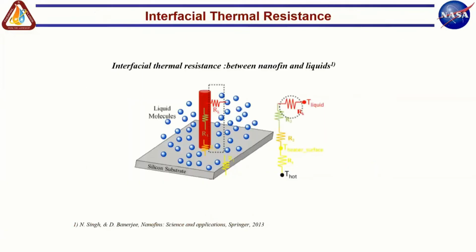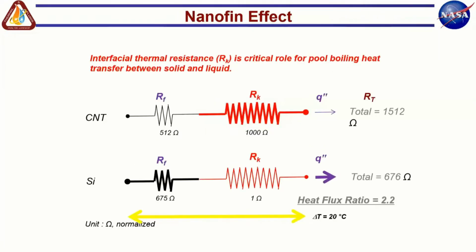So, if you think of this whole nanofin as a resistance network, if you do the numbers, the ones that dominate are the fin resistance and the Kapitza resistance, which is marked as RK. And if you do the numbers, the back of the envelope estimates using a one-dimensional conduction model. If you look at a carbon nanotube, and I have normalized the numbers here, these are non-dimensional numbers, even though I'm calling it ohms, it's not really ohms, just for your visualization purposes. So if I think of this as a resistance network, the resistance within the carbon nanotube is about 500 ohms. The Kapitza resistance for carbon nanotube is about 1000 ohms. So you're getting a total resistance of about, let's say, 1500 ohms.